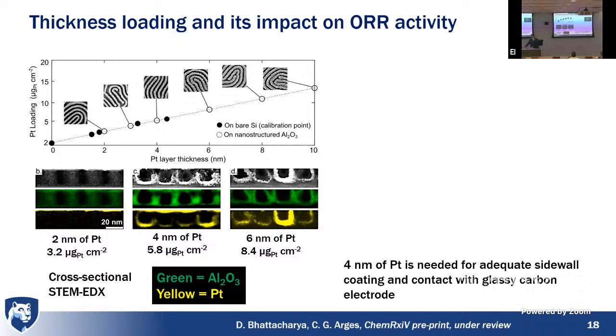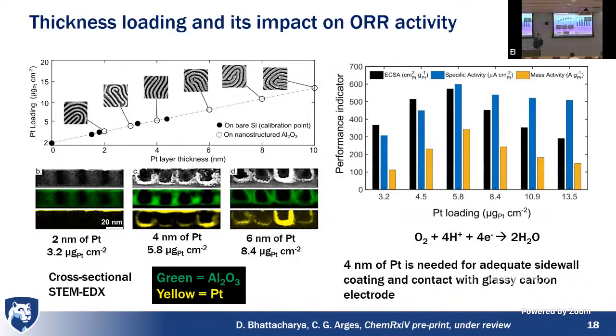But what we found in the rotating disc electrode, and I know this is a lot of data here, is that 4 nanometers, which gave us 5.8 micrograms per square centimeter, was the right balance, right? We got enough sidewall coating where that platinum could make connection with the glassy carbon tip underneath, but it wasn't too much that the platinum underneath was being wasted, right? We just wanted the surface to participate in that oxygen reduction reaction.